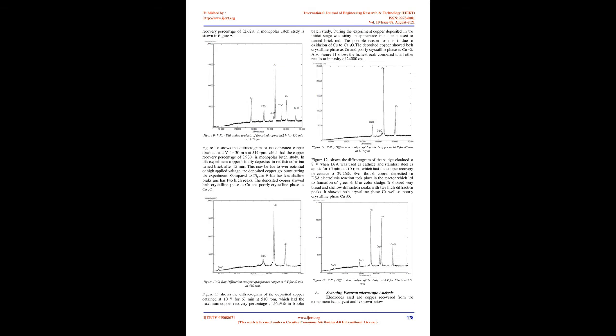The drop in the amount of copper deposition is probably a result of a substantial decrease of mass transfer rates of copper, which is probably behaving as rigid spheres. This phenomenon causes molecular diffusion to govern the system, and therefore the amount of copper deposition decreased (Mastidi et al., 2008). Effect of DSA as cathode.